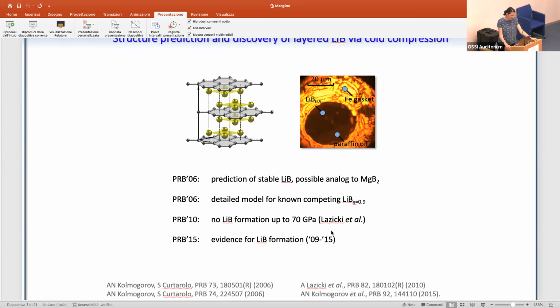A few years later, Lazicki and collaborators performed a high pressure experiment, but they did not find any evidence of the formation of the lithium boron stoichiometric compound up to 70 gigapascal. This came as a surprise, because I was aware at the same time of the experiments done by Alexei's team that had found the first evidence of the formation of lithium boron. However, it took a few more rounds of experiments and a lot more modeling work to conclusively show that lithium boron indeed formed, and they were also able to anneal the sample down to ambient pressure. That work was published much later, in 2015, but as you can see, it took about 6 years to really figure out and synthesize this material.